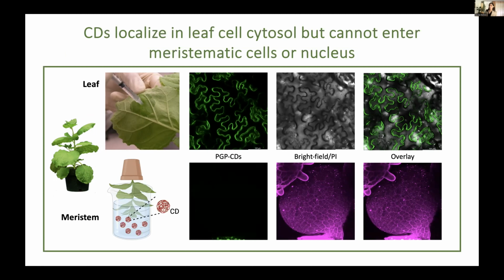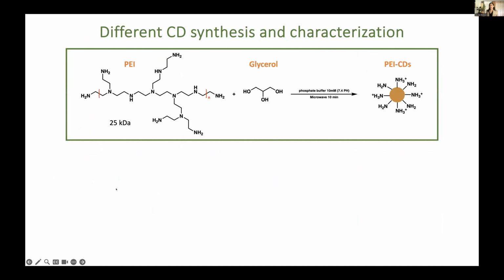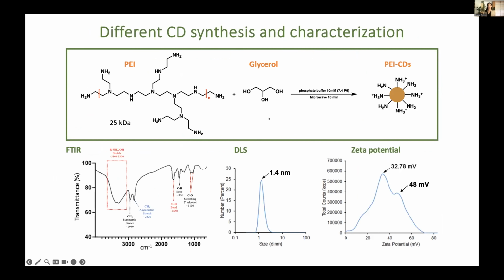So then we suspected that the surface charge of 20 millivolts may not be enough for efficient cell entry in these meristematic cells. And then we generated a newer synthesis method that just uses a higher molecular weight polymer, and we removed the PEG. So, similar characterization of its identity as well as size. It's around the same size as the previous particles, but you can see that it's more charged. We have 2 peaks around 33 and 48 millivolts. And then we do a lot of other characterizations that I'm not showing today based on TEM, AFM, as well as XPS methods.